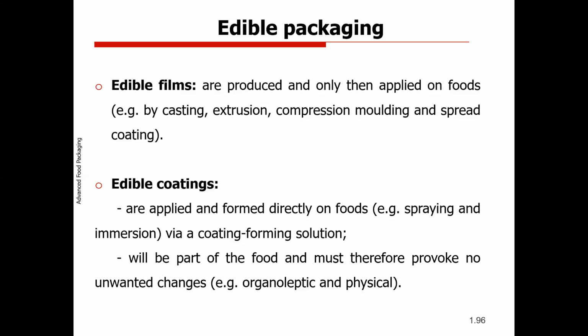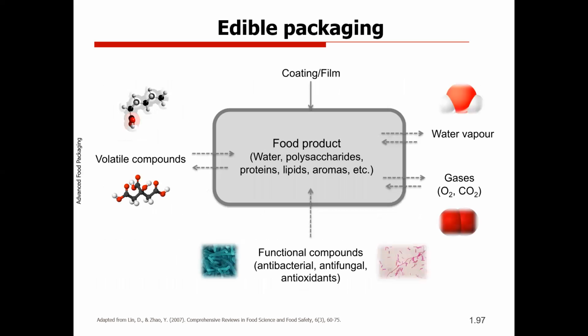They can also be used as a way to put some antimicrobial and antioxidants on the surface of food products, and with this increase the shelf life. This is quite a good image that we can use to understand this. So we have the food product, we have the coating or the film. You can control the water vapor, the gases, and volatile compounds, and you can add some functional compounds, antifungal, antioxidants, and antibacterial for the foods on the surface, because in some food products, the microbial growth starts from outside, and in that case this kind of technology and this kind of packaging can be very suitable.